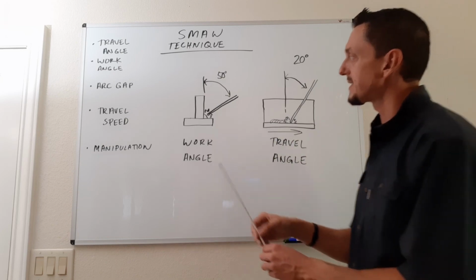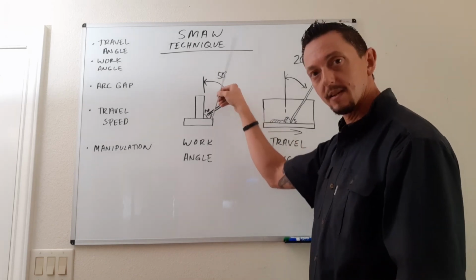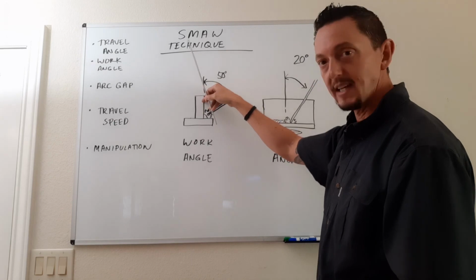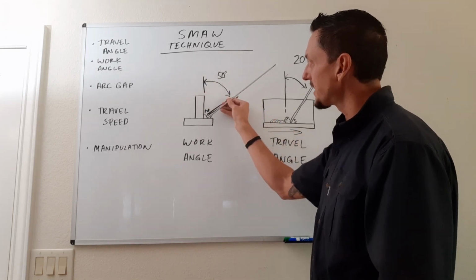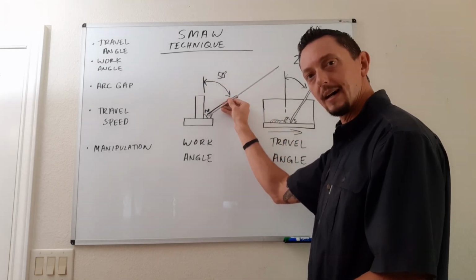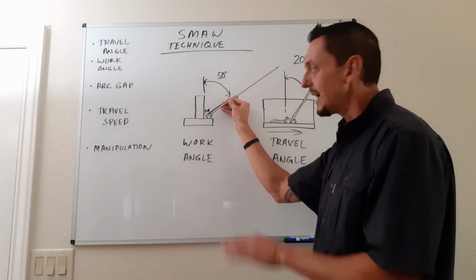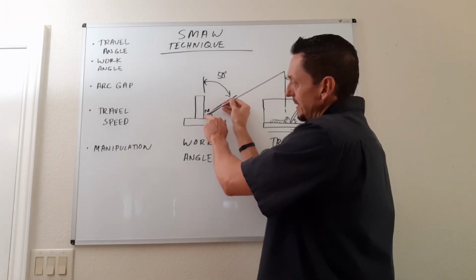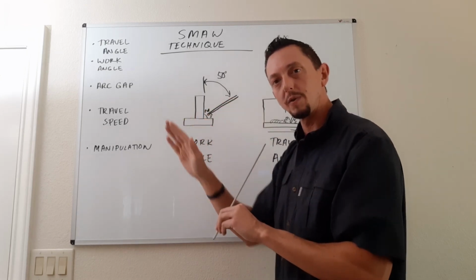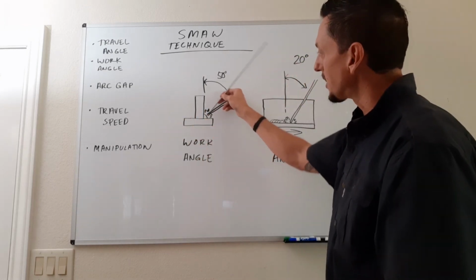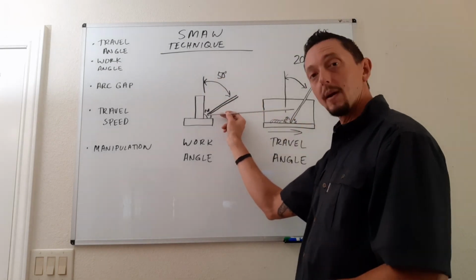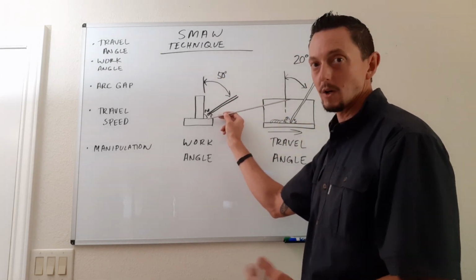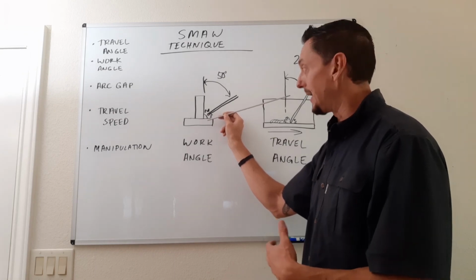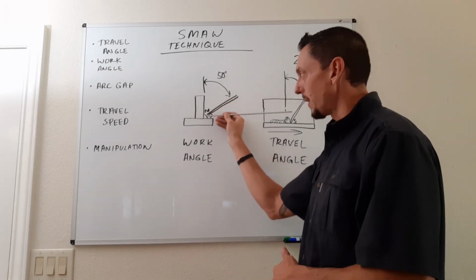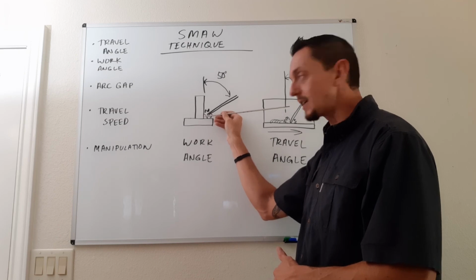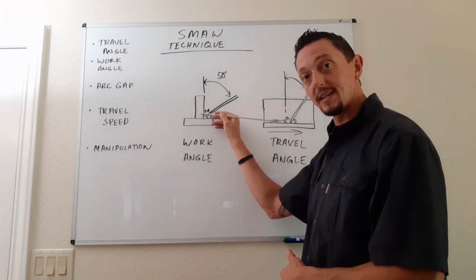Our work angle is in relation to the work piece. Okay, so in this case, with a T-joint, we're going to have about 50 degrees, so just slightly lower than 45 degrees. That way, as our weld metal is being deposited in this corner, as it cools, it comes out nice and flat. And if we go to the extreme, either way with this, we're going to start to see our quality start to lessen because if we're way too low on our angle here, then we're going to be directing most of the weld metal to this top member.